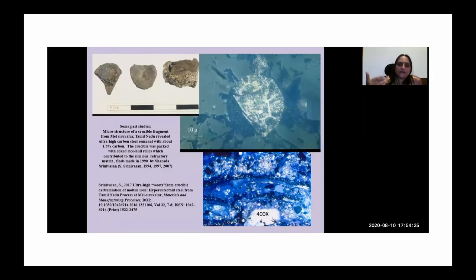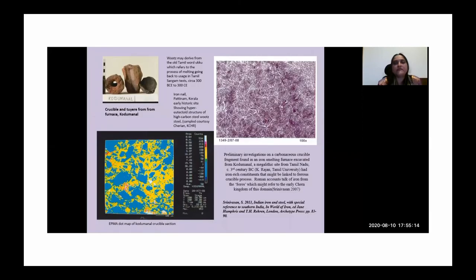And you also find that the glassy matrix of the crucible has a lot of trapped quartz particles and so on. But in this case, it also has these coked rice hull relics, where the rice hull has got fired, and it's also very siliceous, so it adds to the siliceous matrix. The addition of rice hull relics also contributed to improving the refractory properties of the crucible. So this quartz-rich glassy matrix managed to ensure that very high temperatures could be withstood, and that long and high firing cycles could be maintained. Some of these aspects are quite important to understanding how the steel was made.